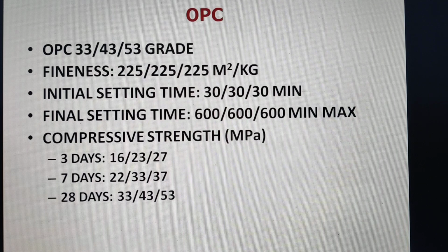In 3 days it should be minimum 16 MPa for 33 grade, 23 MPa for 43 grade and 27 MPa for 53 grade. 7 days strength should be 22, 33 and 37. And finally, after 28 days, it should be 33, 43 and 53 MPa. We know that more than 90% strength is achieved at 28 days. Therefore, we prescribe the 28 days strength.